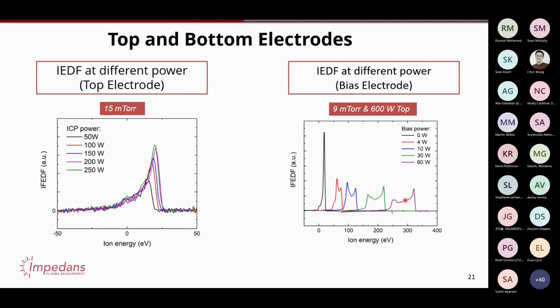So this is now, the top is constant, but we're changing the power on the bottom where the substrate is sitting. And with no bias power, you just have a peak at plasma potential pretty much. And then as you increase the power, you're increasing this DC self-bias, right? So now the electrode is getting more and more negative. And for small increases in power, this is only going up to 60 watts in this tool, you've had a huge increase in ion energy. You've gone from maybe 20 up to over 300 being available with a relatively small power.